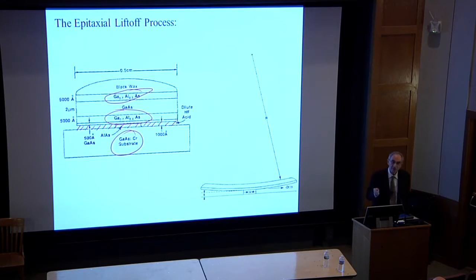But there's one respect in which aluminum arsenide and gallium arsenide are very, very different, and that is in chemical selectivity. So I'll just give you the punchline. If you expose these two materials to acid, aluminum arsenide etches and gallium arsenide does not etch. Okay, so what you do is you come in with some acid, and it etches away the aluminum arsenide, so the acid goes in. It penetrates a macroscopic distance underneath. And now the active part, the top micron, which you needed for your active device, then floats off. And the substrate, which is about half a millimeter thick or even thicker, can be reused.